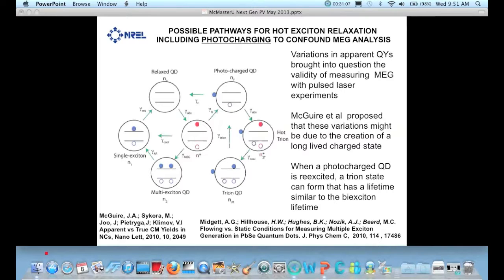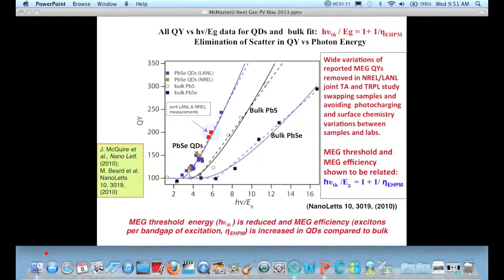The way to get around this, and this was explained in these two papers, is to do a dynamic experiment by moving the sample, either spinning it or stirring it, so that when the pulse comes in, even if there's a trapped electron, the pump sees a fresh volume of sample, and therefore it doesn't see the charged quantum dots, and then you'll get the right answer. So all that scatter, as we show in this paper here, which is a collaboration between Los Alamos and NREL in one of these DOE Energy Frontier Research Centers, got rid of the scatter and showed you can indeed get the same result in different labs. It confirmed that this is a real effect, and the efficiency is much higher compared to bulk semiconductor, which has an efficiency about half of what the quantum dots have for the multiplication process.